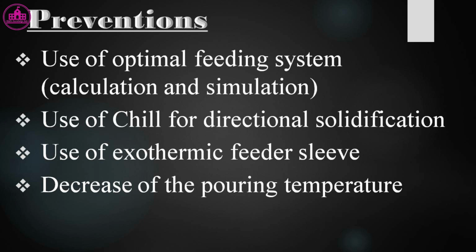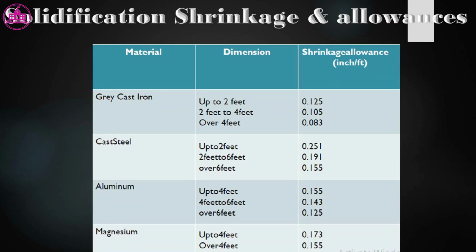Preventions. Use of optimal feeding system. Use of chill for directional solidification. Use of exothermic feeder sleeve. Decrease of the pouring temperature. Solidification shrinkage allowances.